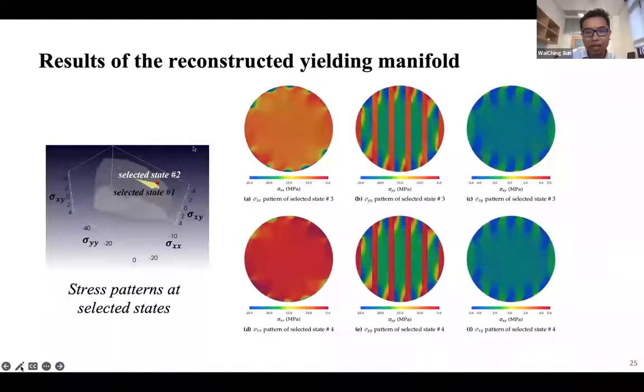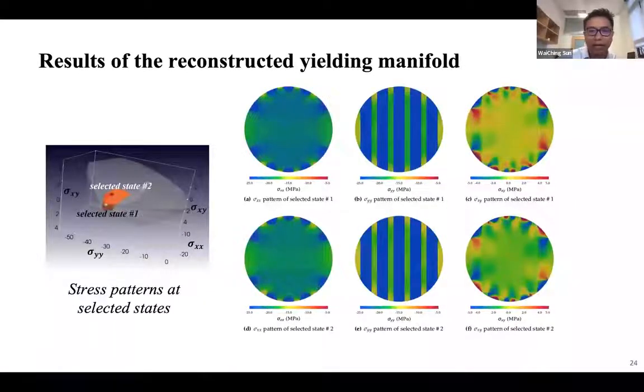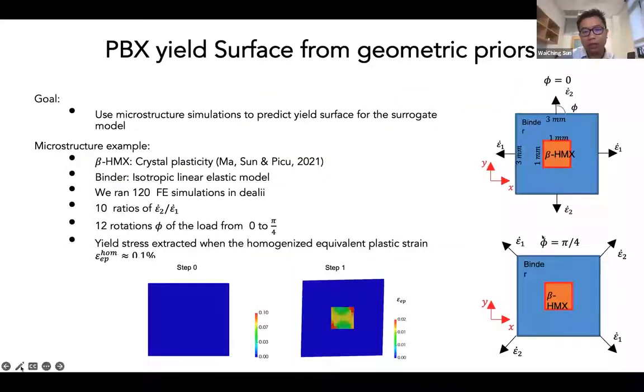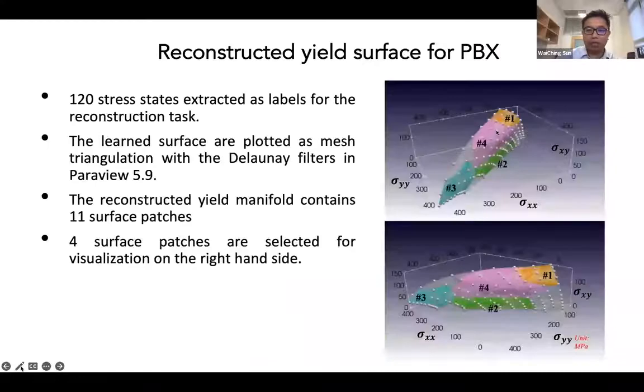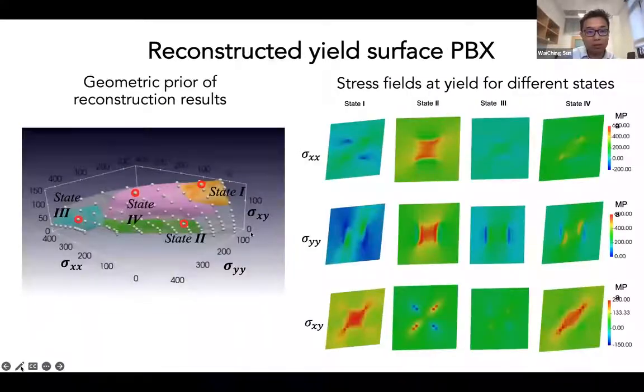However, if we have something that is very far apart, we can see that the pattern could change quite a lot. We can also apply this. This is just another example on HMX with a polymer layer, which is actually used for explosives. In this case, in the 2D simulations, when we try to homogenize it in that patch, you can also see a different geometry that is pretty hard to parameterize by hand. You can also see that for different states, the shape or the plastic flow directions are constrained so that they are consistent with the yield surface.